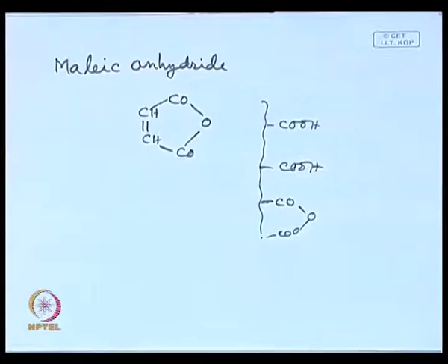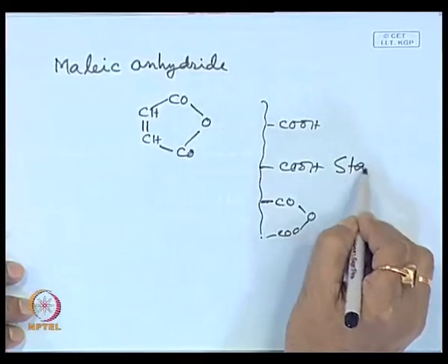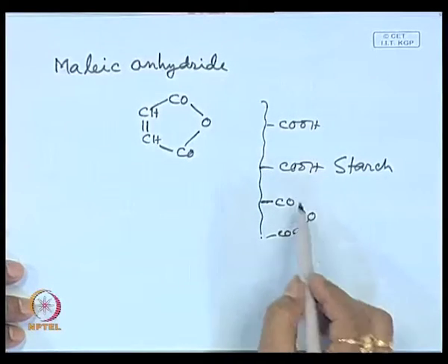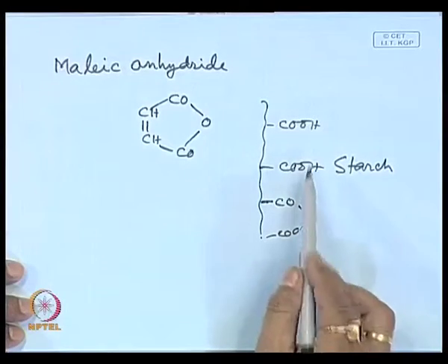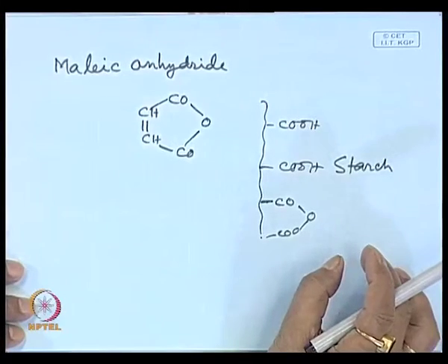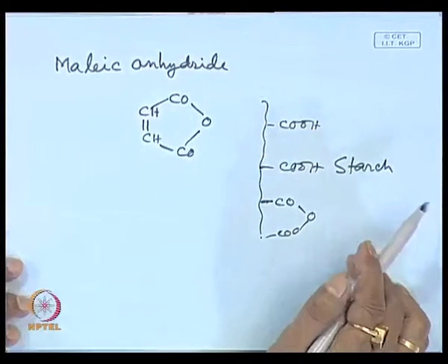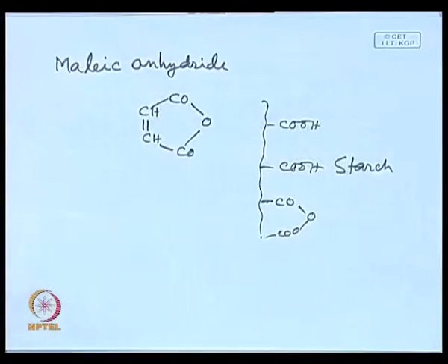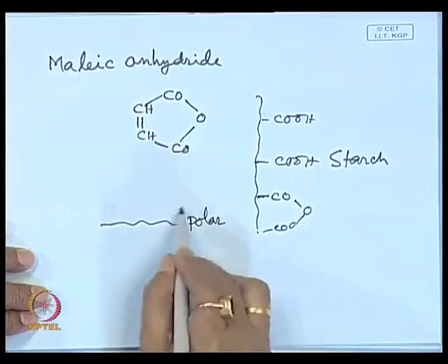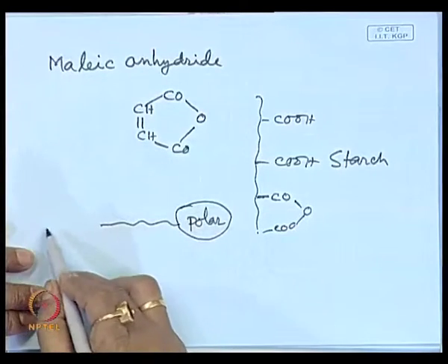Then if you put starch on this side which is polar, this side is polar. So, if polyethylene is modified like this, starch can be accommodated. Starch, you know, has anhydroglucose units, hydroxyl groups are there. So, that can be easily accommodated. So, people took such a maleic anhydride grafted polyethylene or polypropylene, or other compatibilizers which have this polar and this non-polar part.